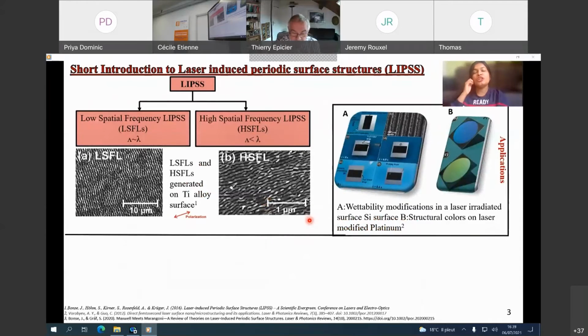So in order to give you a short introduction on laser-induced periodic surface structures, they are nanoripples or nanostructures that are formed on a material when a laser is irradiated on the surface, and they are categorized into two. So we have low spatial frequency LIPSS or LSFLs, which have a period approximately equal to the wavelength of the laser used. And then we have high spatial frequency LIPSS or HSFLs, which have a period much less than the wavelength of the laser used. And in figure A and figure B, you can see the topography of these LSFLs and HSFLs formed on a titanium alloy. And you can see how their periods are different, and their orientation is also different for LSFLs and HSFLs.